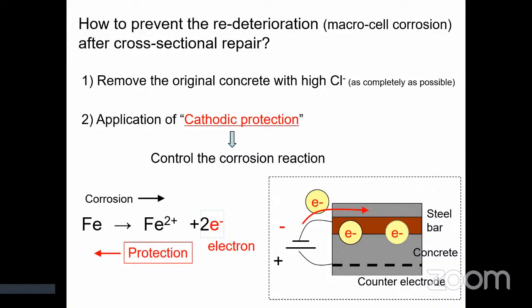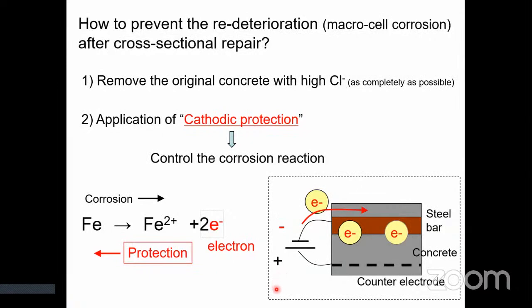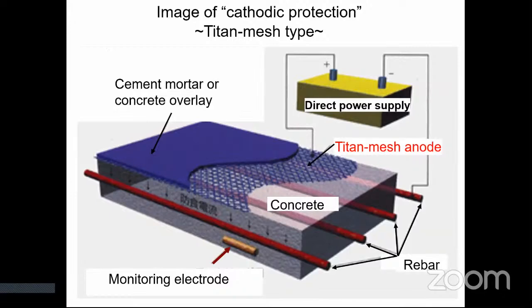In the chemical reaction of iron, this direction is the corrosion reaction. On the other hand, the opposite direction is not corrosion. Therefore, if electrons are supplied to the steel, the corrosion reaction can be prevented by using this electric circuit. This slide shows an image of cathodic protection, titanium mesh type. Electric power is supplied to the steel bar by using a titanium mesh anode.